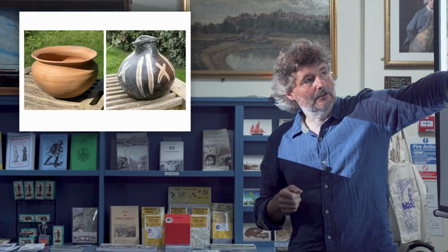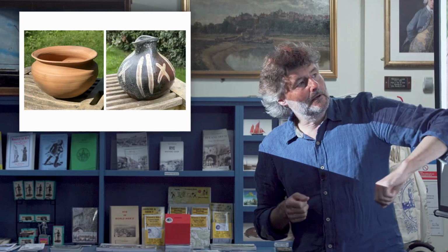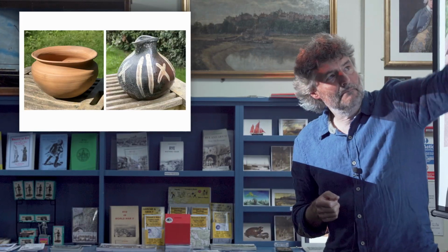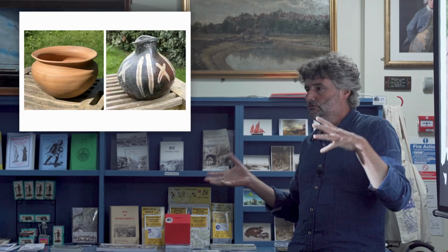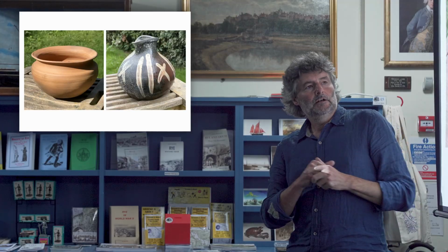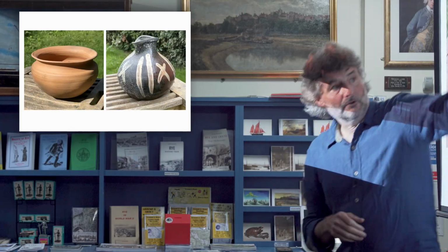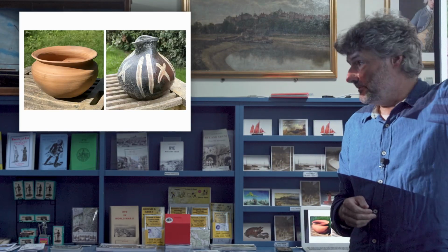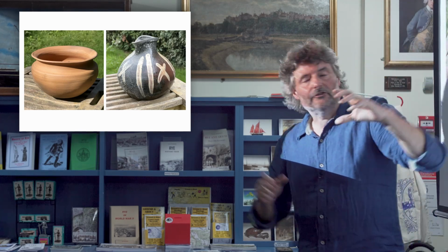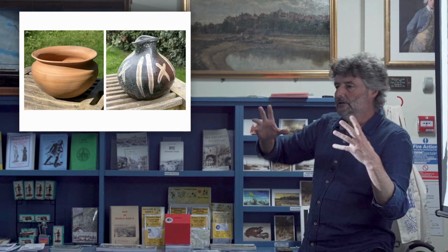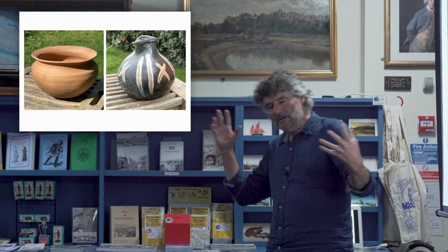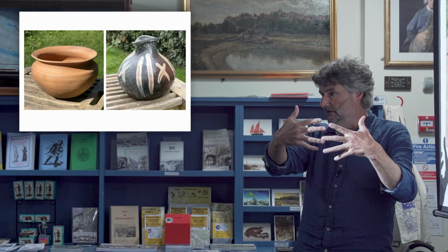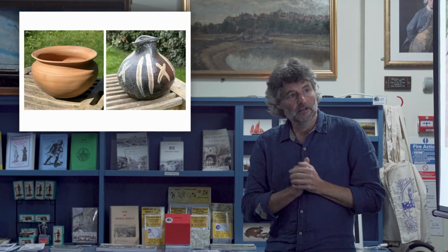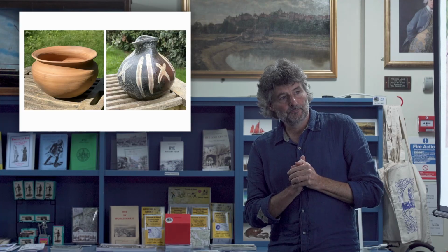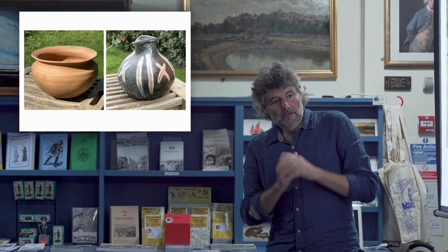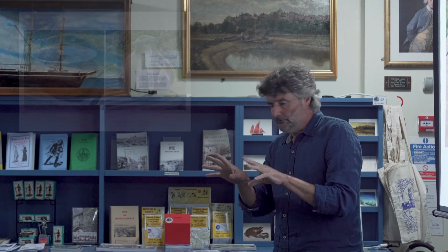So the glaze here has bubbled. The blackness here may be a reduction effect, which is when you starve the kiln of oxygen. But on this side, it's actually quite respectable. That's what it was supposed to look like, which suggests that the pot may have simply been in a position where it was exposed to a massive flame from one side and not on the other. So it just suffered from sort of differential heating. So I could show you lots more pictures of pots, but I'm not going to do that.